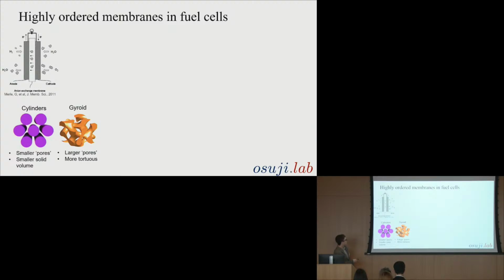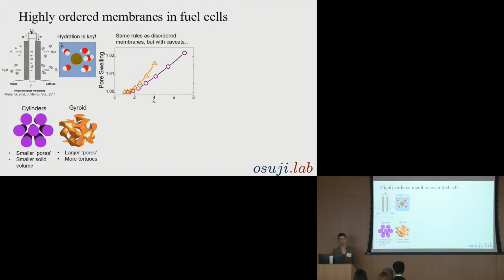So the cylinders have smaller pores, but a smaller solid volume present, while the gyroids are a bit more tortuous, but are larger. They use their space better. What we look at is a measure of hydration, a lambda value that is effectively the number of waters per charge center present. And we find that the rules driving our ordered membranes are very similar to disordered membranes. So we see here on this graph that we swell our membranes, and they respond by increasing conductivity in kind. But there's a caveat.